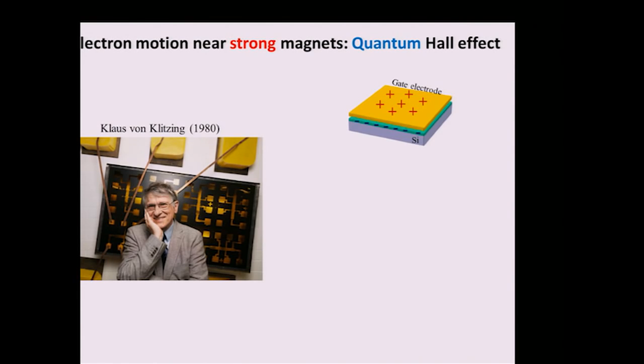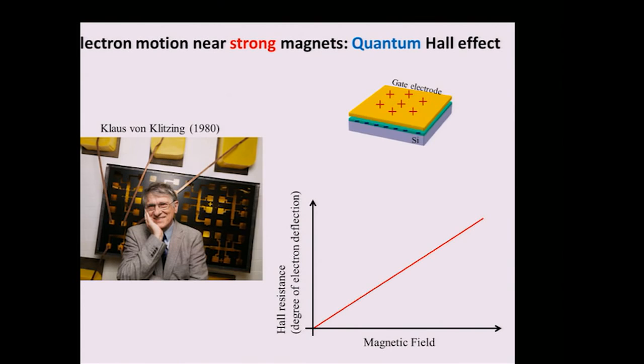And using that very thin layer of the electron sheets, he measured the Hall measurement. He did use an extremely strong magnetic field, several Tesla, which is probably about 10 times larger than the magnetic field I used there, and at very low temperature. First he actually did it at the higher temperature, and then it's the usual Hall effect, and the slope will tell you how many electrons are in this system.